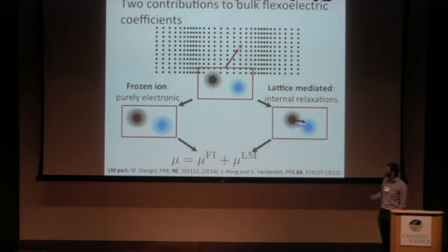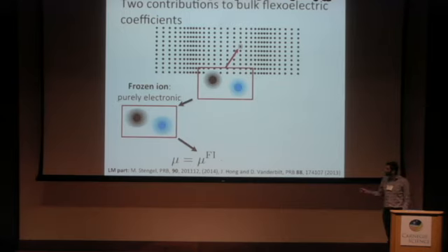So this was touched upon in the previous talk, that in that case, you have two contributions. You have a frozen ion contribution, or in the previous talk, a clamped ion contribution, which is, again, the purely electronic response to the strain gradient. And then you also have a lattice-mediated contribution from the internal relaxations caused by the local strain and strain gradients. So in this talk, I'll be focusing on the frozen or clamped ion contribution. If you're interested in discussion about the lattice-mediated part, then I'll refer you to these references.